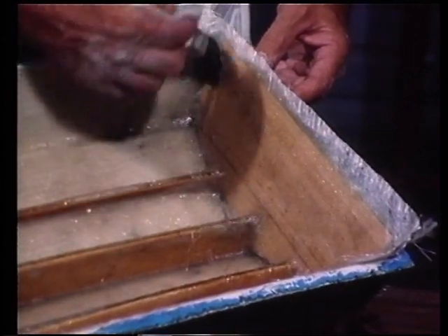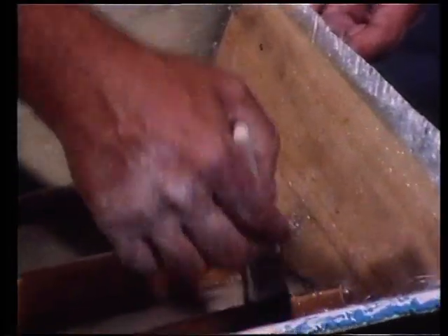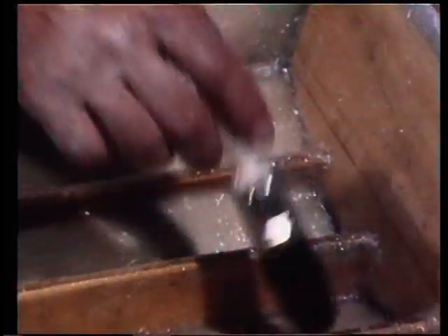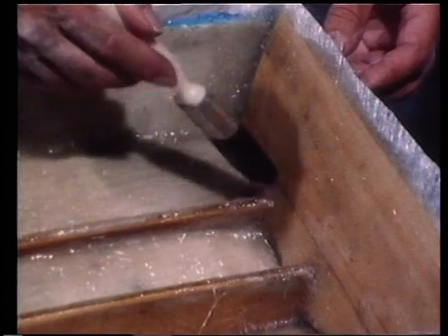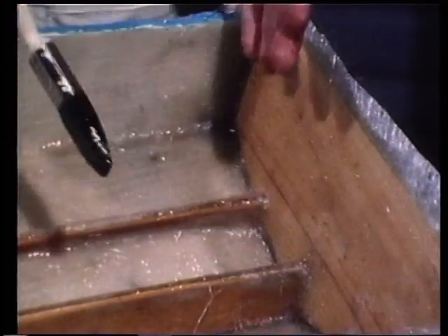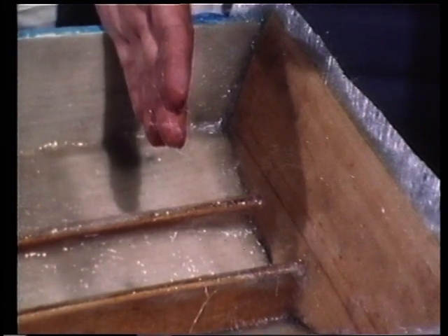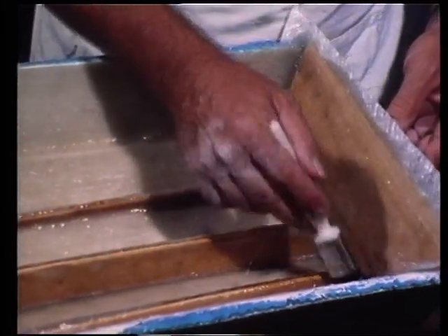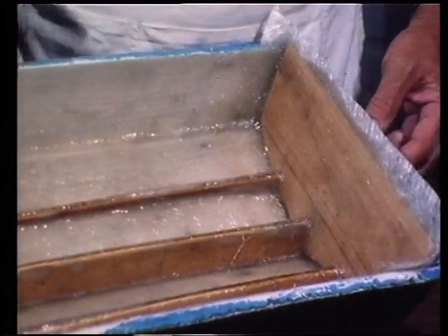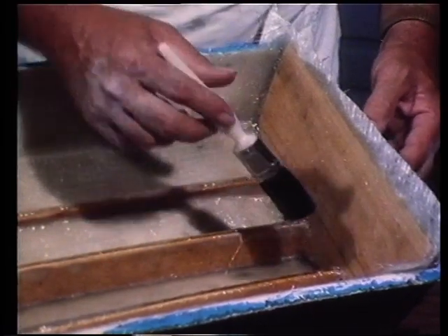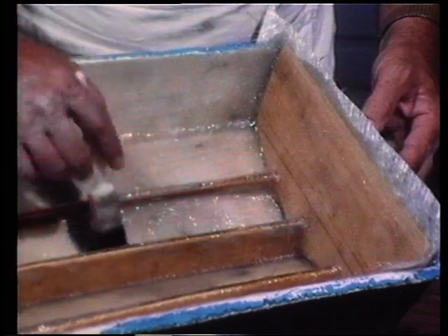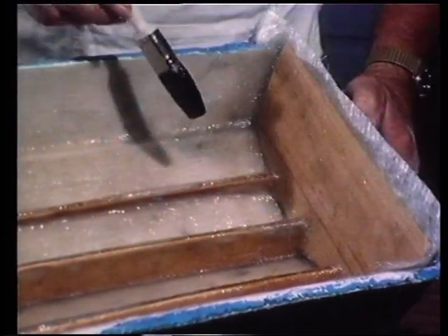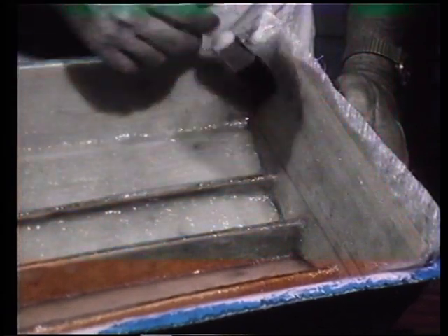Now, you must work with maximum sizes of sheets of material. For instance, if this were a full-size boat, I'd be looking at going from the keel to the chine by 1 metre wide, which is the width of the roll of mat that you buy. Overlap it by around 75 millimetres and go another metre up the length of the boat, and so on, so that you're working with sizes of materials and sizes of sheet that are easy to handle as far as the glass itself is concerned, and are also easy to handle as far as the amount of resin that you mix, which really should not be more than about 2 kilos at a time, and of course your resins and your tools. Now we'll let that sit in the mould for 24 hours.